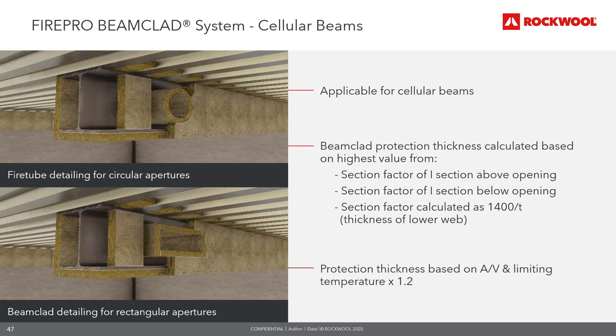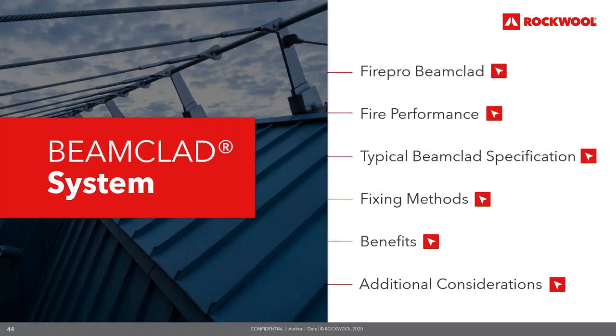The ASFP Yellow Book will give guidance on how the section factors, or the A/V factors, sorry, should be calculated. That will look at either the section factor of the I section above the opening, the I section below the opening, or it will take the section factor calculated as 1400 divided by the thickness of the lower web, whichever is the worst case, in order to calculate the thickness of insulation that is required, the protection thickness allowed. We then times that by 1.2 to come up with a conservative thickness, so something that we're quite happy would be sufficient to protect that cellular beam.